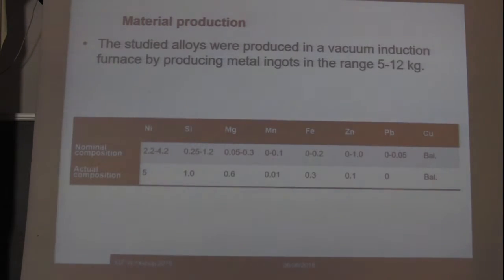So we produced the selected alloy in a vacuum induction furnace, producing big ingots in the range of 5 to 12 kilograms. In the table, you can see the nominal composition of the alloy and the real composition of the alloy we produced. As you can see, only the nickel content is slightly higher than the nominal composition range.